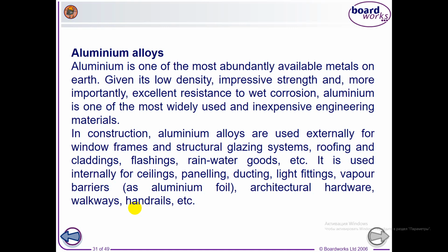It resists corrosion, especially if it's anodized. However, it has only 1/3 of the stiffness of steel, and it melts at the relatively low temperature of 550-600 degrees, in comparison to approximately 1500 degrees for steels. Its performance in fire is therefore not good, and so it cannot be used structurally in building.